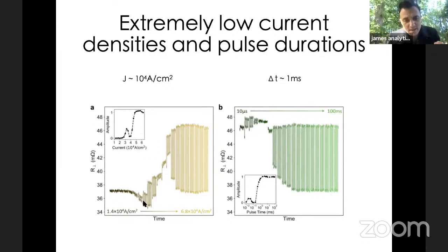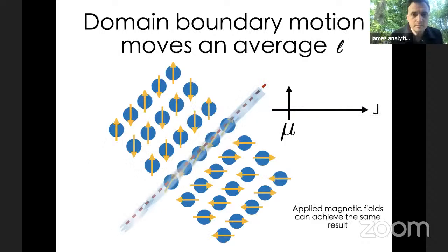And what you see is that the switching turns on, then somehow turns off again, and then turns back on again. And you can apply the same trick with, instead of using current density, you can actually keep the current density fixed, but change the pulse duration. So how long you apply one of those current pulses, and you get a very similar kind of effect. It turns on, then turns off, then turns on again. So we didn't understand this, we just published it, but there was certainly something very unusual going on. But I'll come back to that because I think we have an answer now.